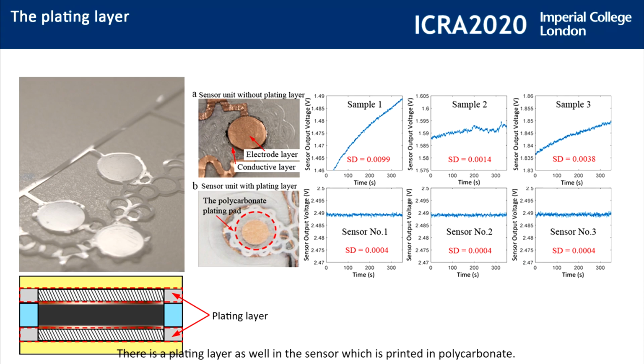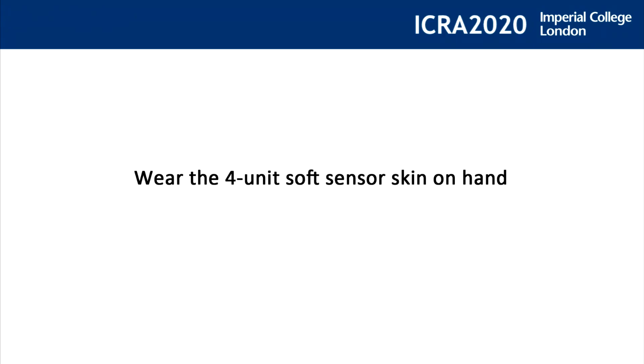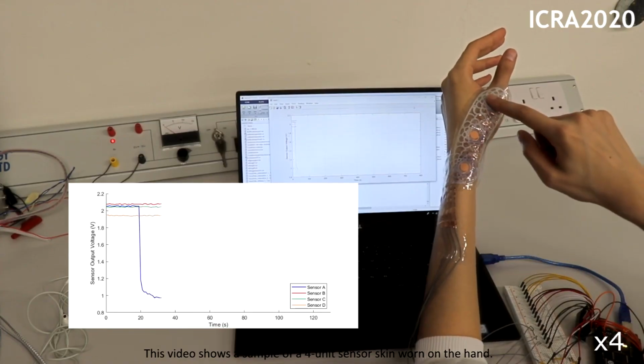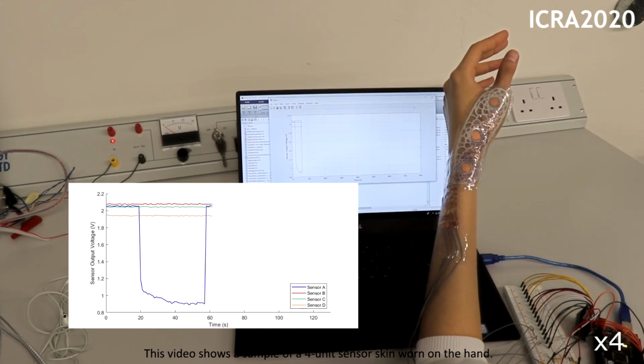There's a plating layer as well in the sensor, which is printed in polycarbonate. Its function is to prevent signal drift at no loading. Without the plating, an upward drift was found in all sensor samples. The plating pad printed with a polycarbonate material builds a relatively harder surface which supports the electrode layer and the conductive layer, providing an even contact between the two layers and also preventing slight horizontal deformation of the sensor unit, therefore reducing the drift. This video shows a sample of a 4-unit sensor skin worn on the hand.